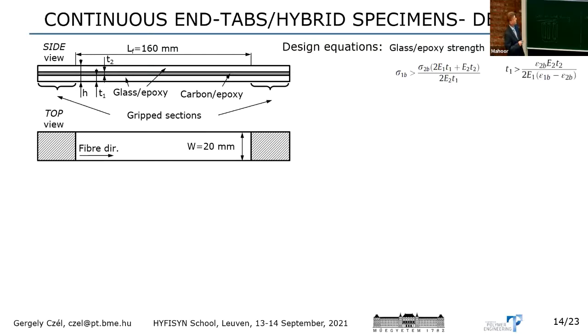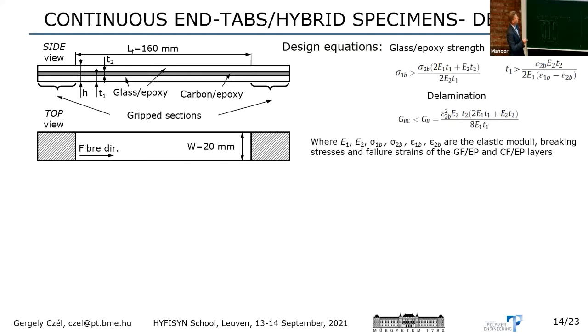Also, we can formulate this to have the minimum thickness of these protective layers if we know the strengths or the failure strain of the components. It's actually based on the failure strains, which we can just use the fiber datasheet values as a first estimation. I usually do that. And if we want to go further, of course, we can characterize the available materials further. Okay, and then this is the more tricky one.